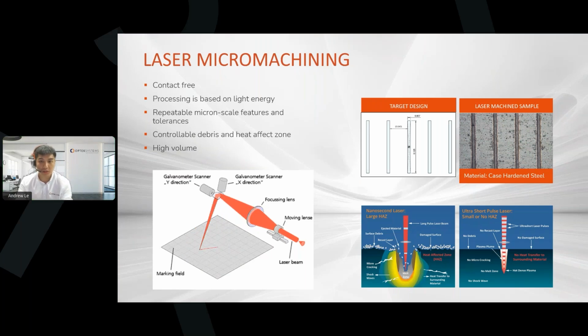An example of what we can see in application can be shown in the top right pictures, where we're looking at a case hardened steel sample, which has been milled to very specific dimensions with minimal heat effects to the actual edges of the workpiece, and no deformation or residual debris effects.